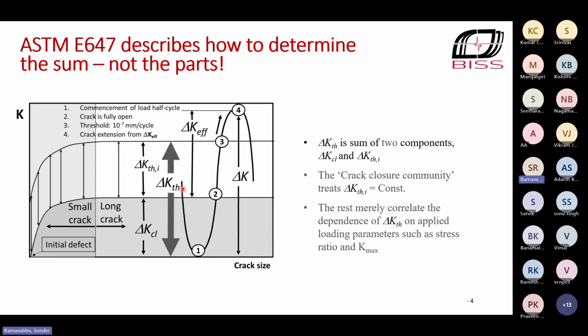That is not even recognized by prevailing standards. One part is associated with crack closure, particularly as the stress ratio at which you determine threshold comes down below 0.6, 0.5. The crack begins to close under tensile loads, and that affects how the measured value of delta K threshold. And unfortunately, that is sensitive to how you do the test.